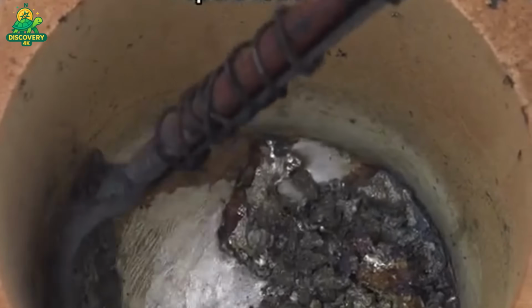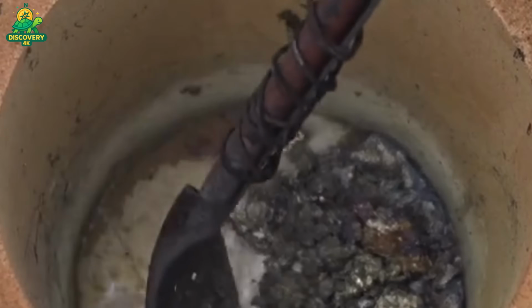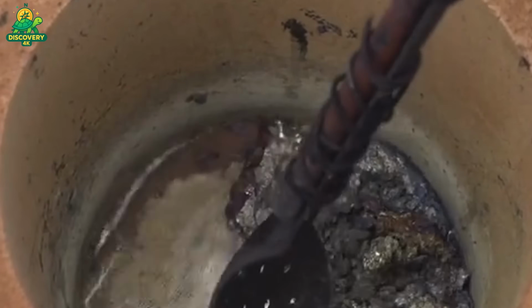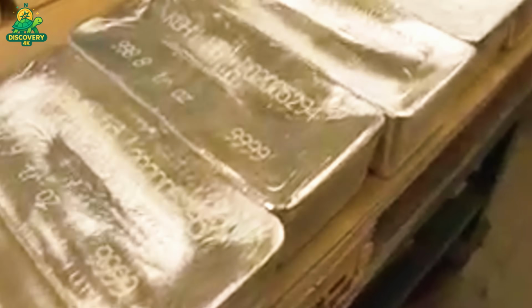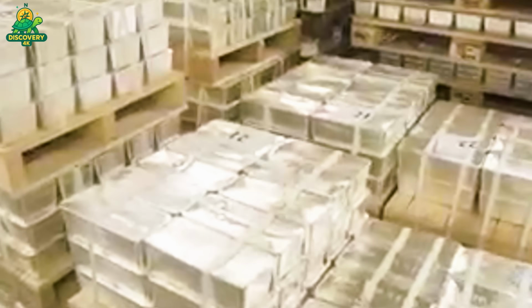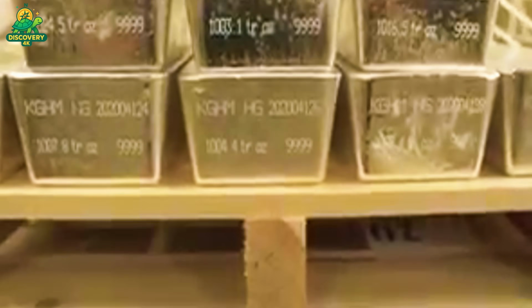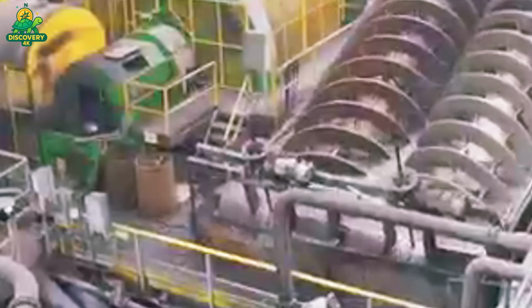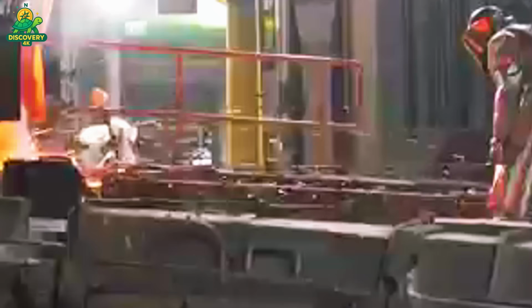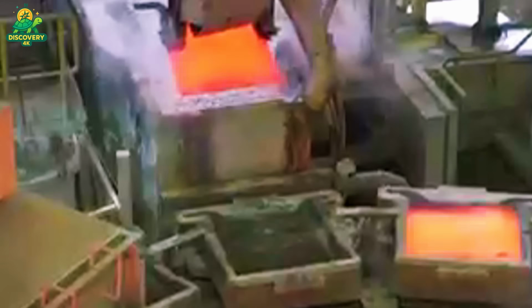Refining begins with electrolysis. The rough silver ingots become anodes, electrodes that dissolve when electric current is applied. They're suspended in a tank of silver nitrate solution, alongside thin sheets of pure silver, which act as cathodes. As electricity flows, silver atoms from the impure anodes dissolve into the solution and redeposit themselves onto the cathodes in pure form. Over the course of several days, these cathodes grow into thick, gleaming sheets of high-purity silver. Meanwhile, any impurities either fall to the bottom of the tank as sludge or remain suspended in the liquid.